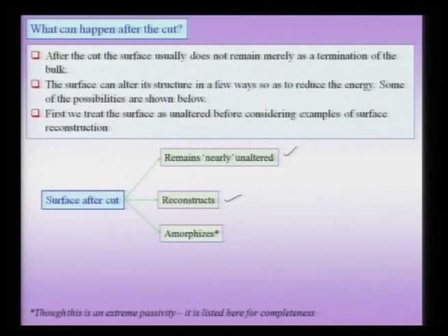obviously takes place so that the energy of the surface can be reduced, because now the cutting involves increasing the energy of the system, because now you have broken the bonds, and this reconstruction can actually lead to the reduction in surface energy. In extreme circumstances, we can also visualize that the surface may actually become less ordered with respect to the bulk, but this is an extreme possibility and we will not consider this further.